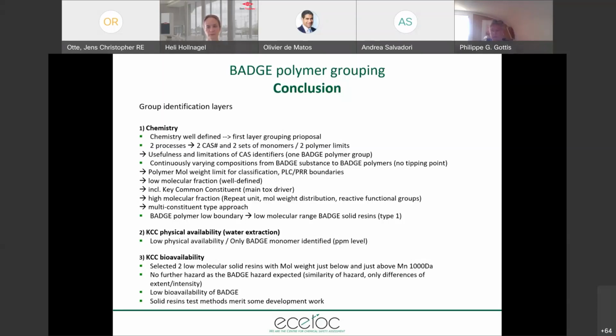As a second layer, the physical chemical properties come into play for refined grouping or subgrouping. As a result, the lower boundary of the polymers in scope is defined as the low molecular type 1 BADGE solid resin. These are the physical chemical properties which help us for that purpose. The physical availability of BADGE N0 as key common constituent was measured upon water extraction test and proved to be extremely low, ppm. And at the third grouping layer, low-tier tests were performed for the endpoints which are positive for BADGE substance. Hazard similarity supports selected grouping. Only differences in the intensity of hazard are expected.